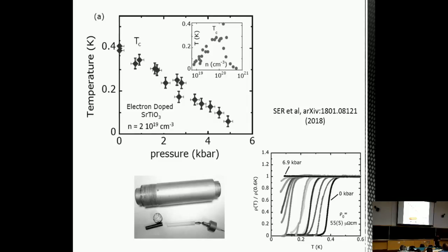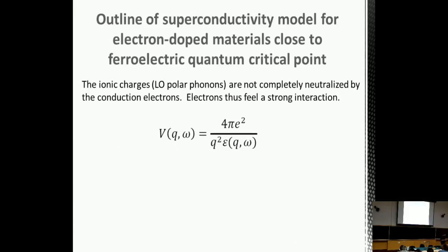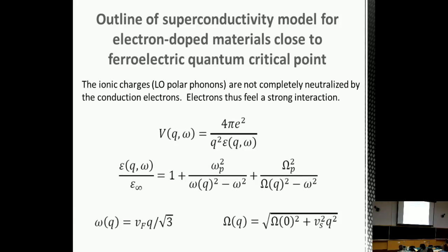So to go back and think about this problem, we considered how the electrons interact with the polar optical phonons and the electron degrees of freedom in the lattice. So here is the interaction function between two electrons added to strontium titanate, and it depends here on the dielectric function, the wave vector and frequency dependent dielectric function. And the dielectric function is given by contributions from two terms, the ions, the polar phonons, and the electrons, which are plasma modes. So omega p here is the plasma